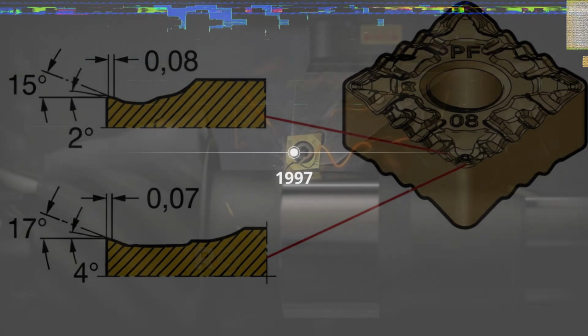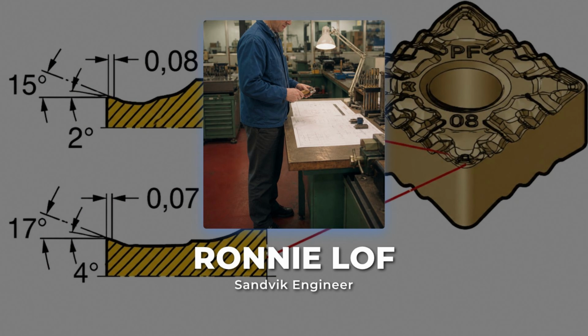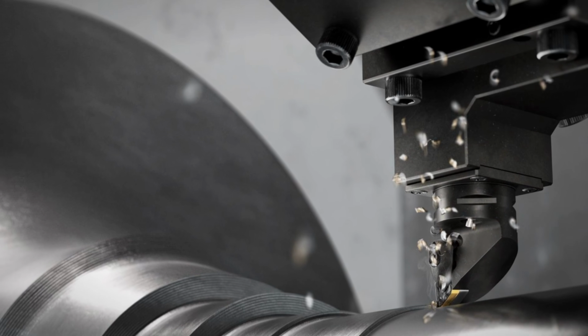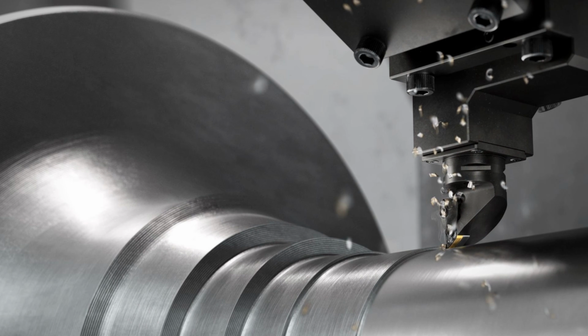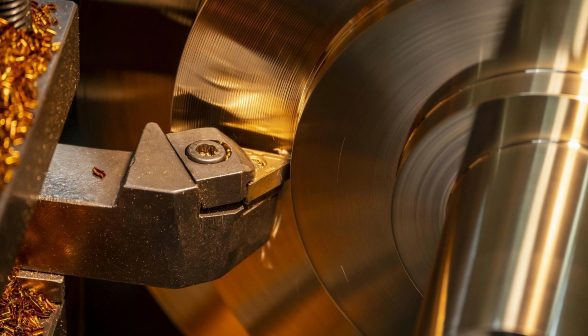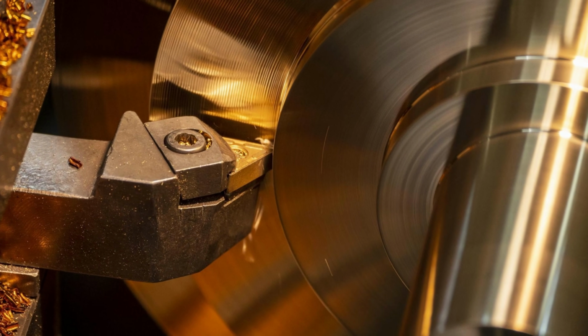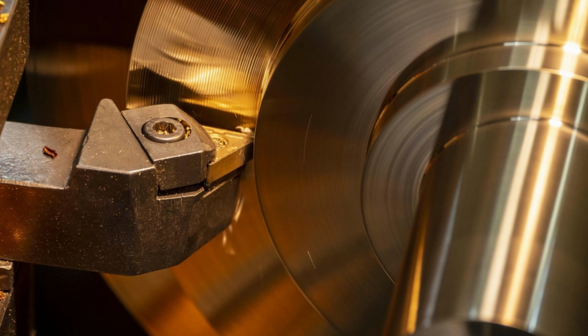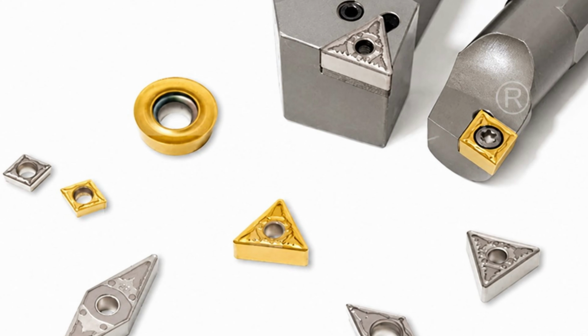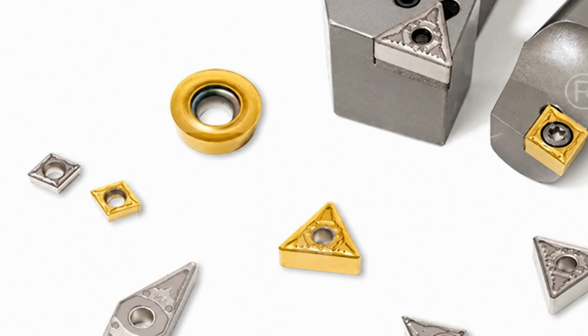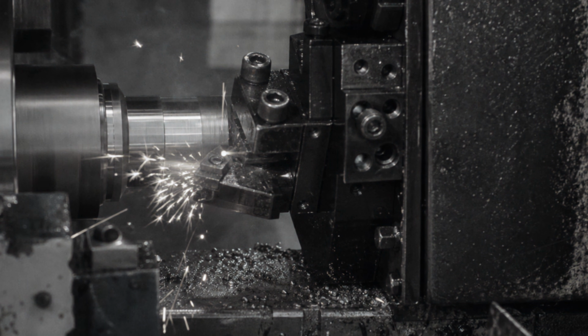In 1997, Sandvik introduced wiper inserts, developed by engineer Ronnie Loff, replacing the single nose radius with a train of blended radii that iron out the feed lines. The rule of thumb stuck fast: double the feed at the same finish, or keep the feed and halve the roughness. Above carbide sits a family of materials for the work carbide can't survive.